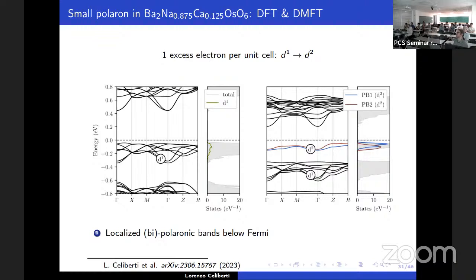In this case, it's a bit different because we started from a d1 structure. So when you add one electron, you go to a d2 configuration, and you also observe two bands, as in a bipolaronic case. So it was in this kind of loose way that, when they form a bound state, they are close to each other. I can understand that it's a bit loose, as the definition always is, like in a superconductor, you have two electrons that interact with the lattice and attract each other. But basically, the name comes from observing a band structure which is really similar to that case, with the caveat that the situation is a bit different from usual previous calculations.